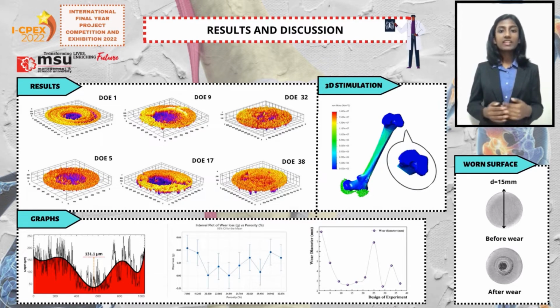The samples are then studied under a microscope to get a microstructure, and they are transformed into 3D to get a better image of the worn surfaces. In addition, 3D bone simulation was also done to determine the stress distribution on the bone when the material is placed. The load that has been applied is 500 Newton, and it can be seen in the result that it is safe to be used.